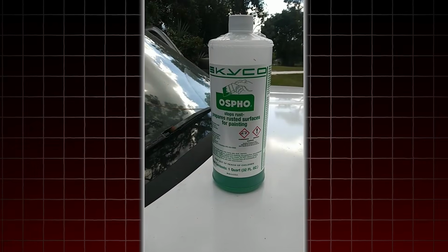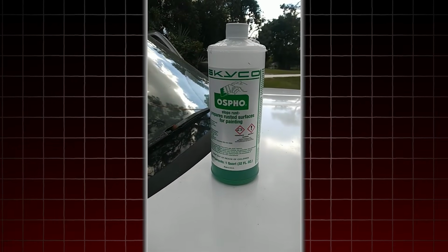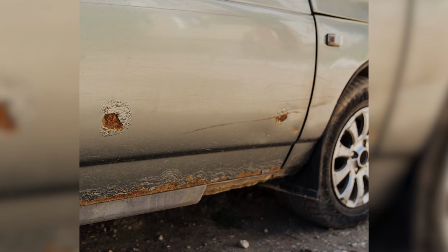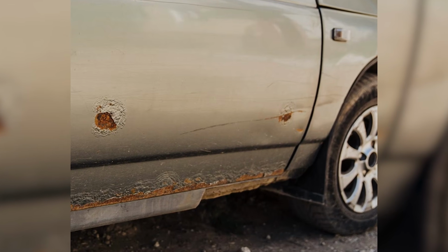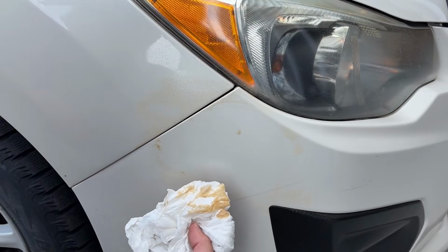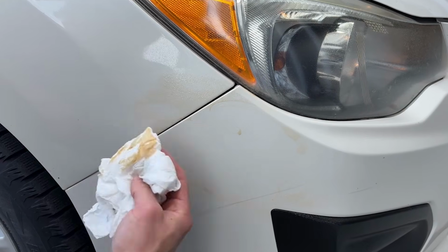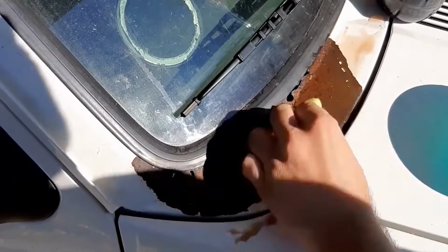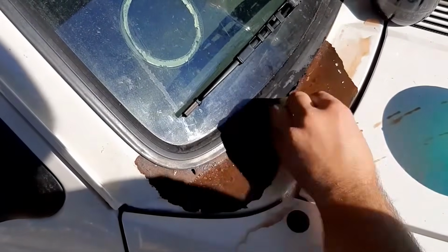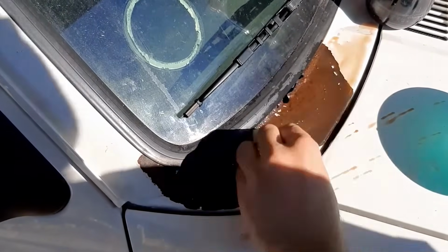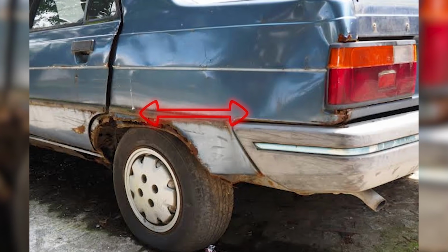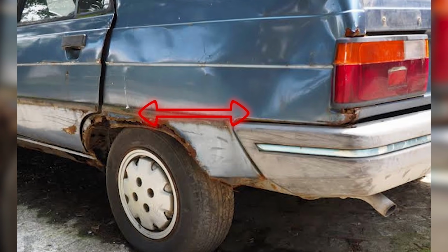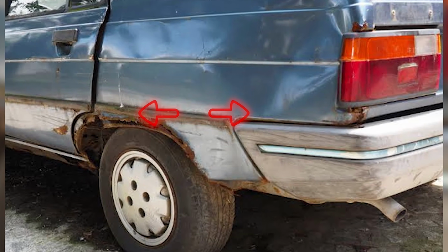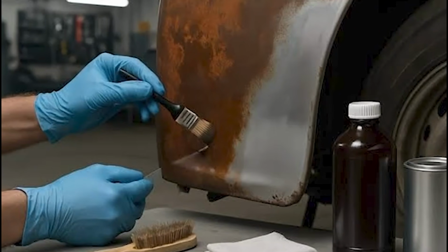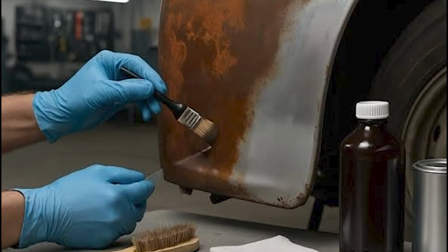Ospho must be completely neutralized and removed before any top coat is applied. Phosphoric acid residue left on the surface reacts with most top coat primers and creates adhesion failure at the primer layer. The neutralization process requires multiple wash cycles, with clean water followed by a baking soda solution rinse. On a frame that cannot be easily rinsed and where water pooling in cavities creates its own rust risk, this neutralization requirement is a significant practical complication.